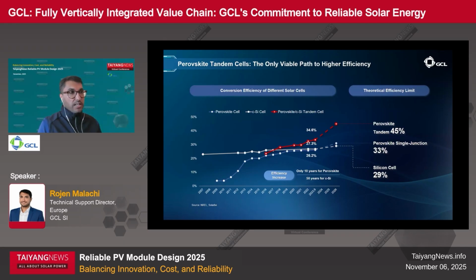Perovskite cells, on the other hand, have shown rapid progress, reaching efficiencies close to 26% in just 10 years compared to 50 years for silicon. However, single junction perovskite cells also have a theoretical limit of around 33%. The real breakthrough comes with perovskite silicon tandem cells, which combine the strengths of both materials. By stacking two complementary absorbers, we can capture a broader spectrum of sunlight, pushing efficiencies up to 45%, far beyond what silicon alone can achieve. This is why tandem technology is considered the only viable path to significantly higher efficiency and lower cost per watt in the future.